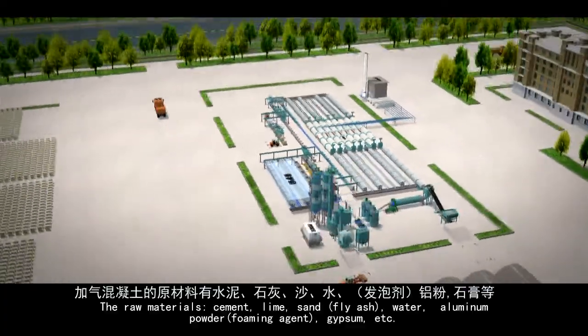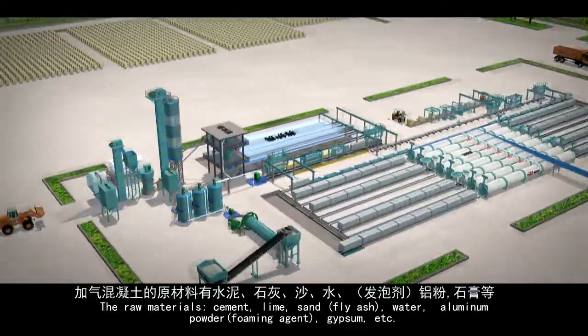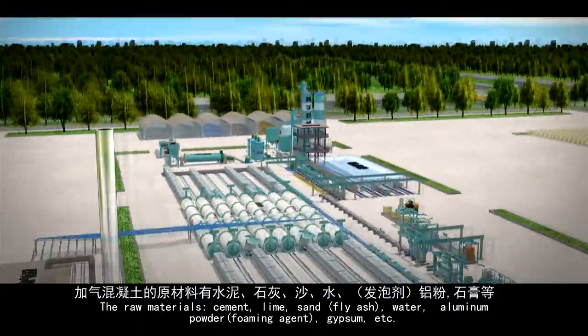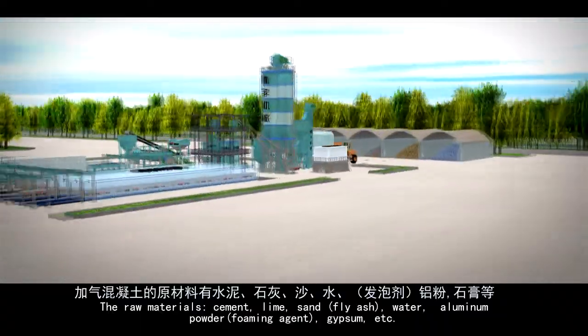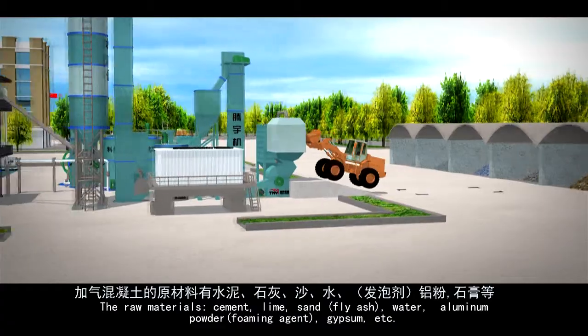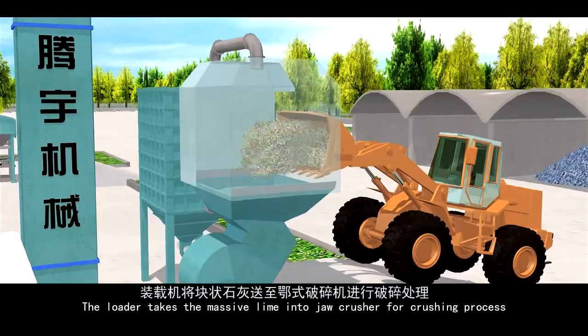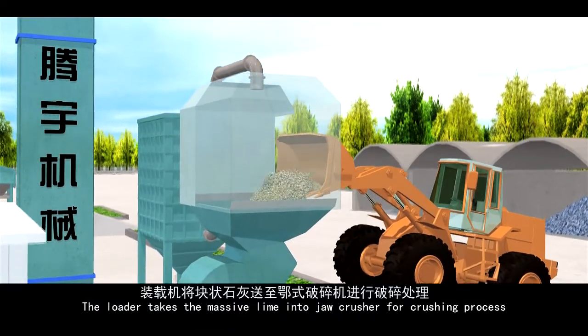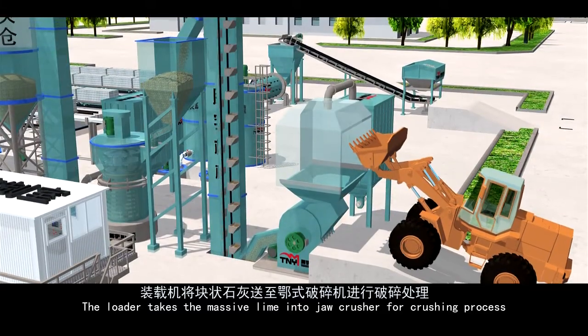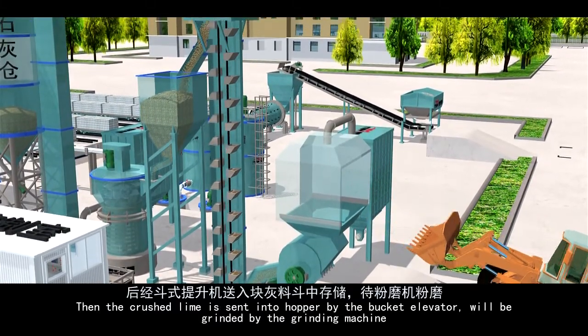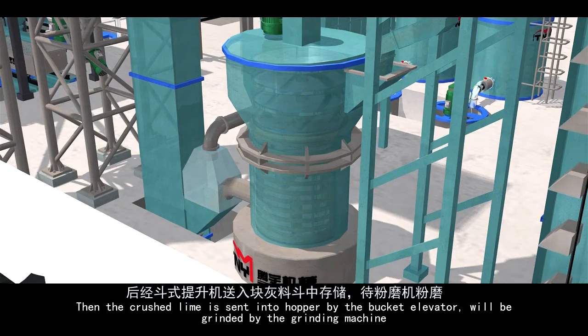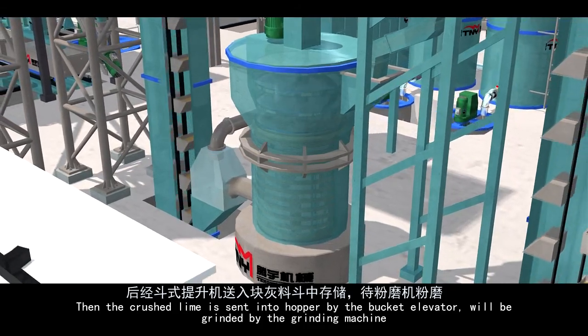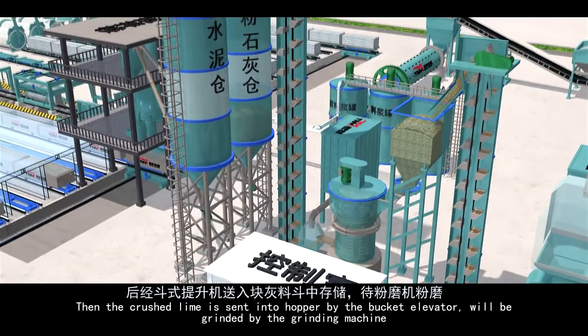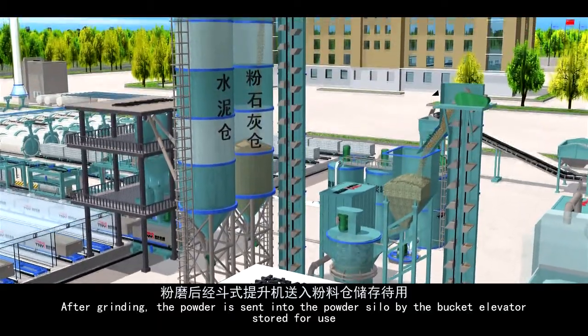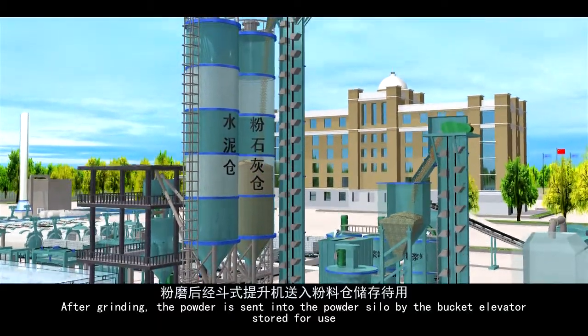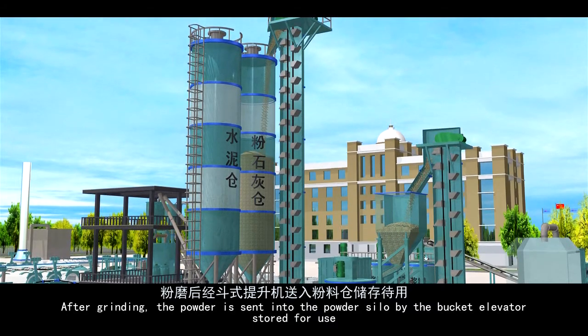The raw materials: cement, lime, sand, fly ash, water, aluminum powder, foaming agent, gypsum, etc. The loader takes the massive lime into the jaw crusher for the crushing process. Then the crushed lime is sent into the hopper by the bucket elevator, to be ground by the grinding machine. After grinding, the powder is sent into the powder silo by the bucket elevator and stored for use.